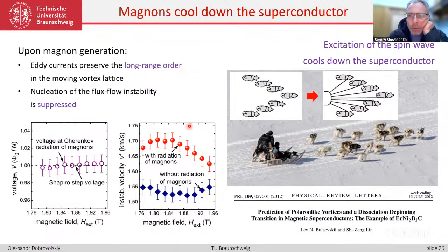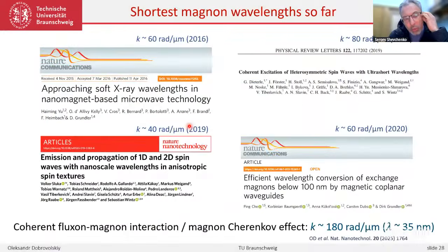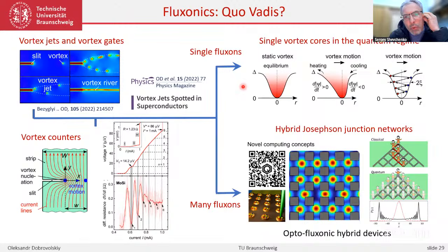That's very nice. And about quantumness, closer to the end, you've spoken about the quantum regime. Where's the quantumness here? So basically, in the regime of very low temperatures, and especially for materials in the quantum limit, the electronic states within vortex cores will be quantized. And there are Bloch oscillations observed, or largely predicted, but for some materials already observed in the limit of very low temperatures for vortices which are moving. So basically, the internal electronic structures of the vortex cores can be deduced on the basis of features observed macroscopically via measuring the current-voltage curve of the materials.